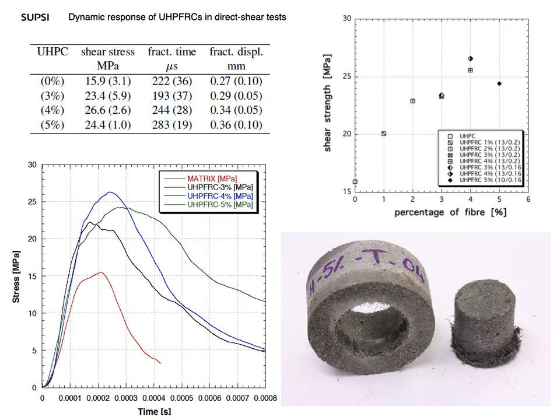can be highlighted observing the comparison between the average shear strength between the different ultra-high performance fiber reinforced concrete with fiber having different aspect ratio. It is confirmed that the shear strength increased with the increasing of the percentage of fibers. It can be noted that the fiber with the same length, 13 mm for example, but a different diameter,